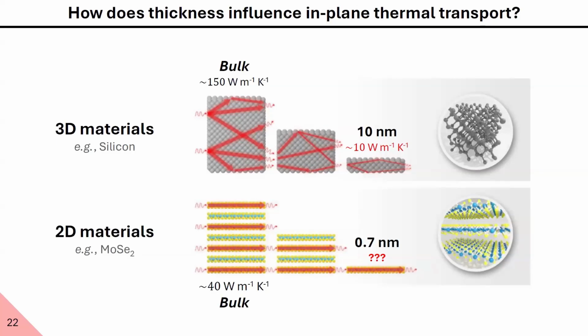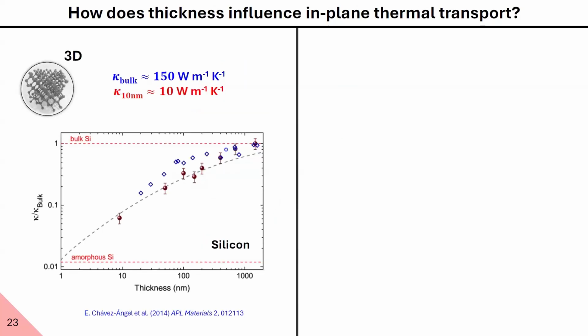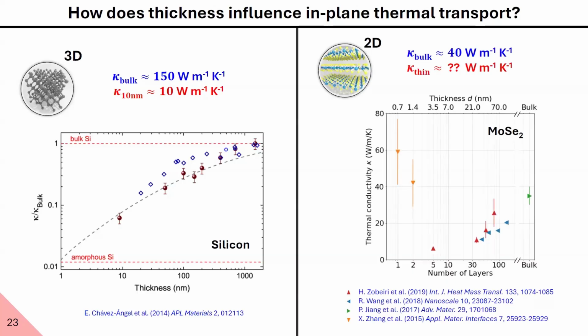So our question is, what happens when you decrease the thickness of a 2D material layer by layer down to the monolayer? Let's find out. For silicon, this is the case. We have around 150 watt per meter per Kelvin. The thermal conductivity starts decreasing as we decrease the thickness, and we have more than a factor of 10 lower thermal conductivity already for a 10 nanometer film. And what was known when we started our research, we had this available literature, and I'm only showing here experimental thermal conductivity values measured, all of them with Raman thermometry. So it was clear that the thermal conductivity decreases while making them thinner, but it was not clear what would happen at the monolayer thickness or in the very thin regime.